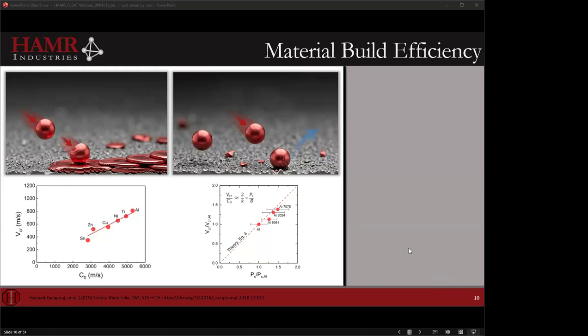There are a few ways to think about this and assess the likelihood or strengths of what you're going to do. We see there's something called a critical velocity in cold spray, basically the velocity where we go from the rebound on the right to the splat on the left. That is a function of the material properties and varies by alloy system, and we have to achieve some velocity in the particle. That velocity is dictated by the temperature and pressure of the gas, density of the particle, and so forth. Within an alloy system, as we increase the strength of the alloy, going from pure aluminum to aluminum 7075, that increases the V crit, or the V crit ratio. So how fast do we need to get the particles? Ultimately, we can relate that, though it's arguable in the literature, to something like the spall strength of the material, and the bulk sound velocity is one approach.